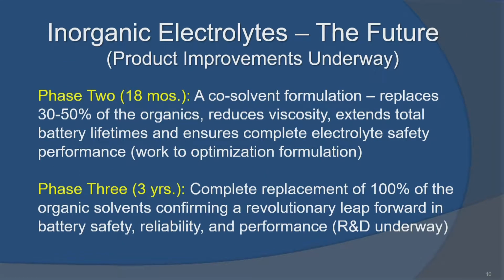The second product, as I mentioned, is a co-solvent. It replaces more of the organic material than the additive. The additive is replacing about 10%, maybe 15% of the organic material. In the co-solvent, we're replacing between 30 and 50%. The result is a reduced viscosity of the electrolyte, extended lifetime, increased safety. The work that was done at the lab brought that product to a point of having 3 candidates for the final formulation. So the work that's needed right now is to narrow that down to one winner.